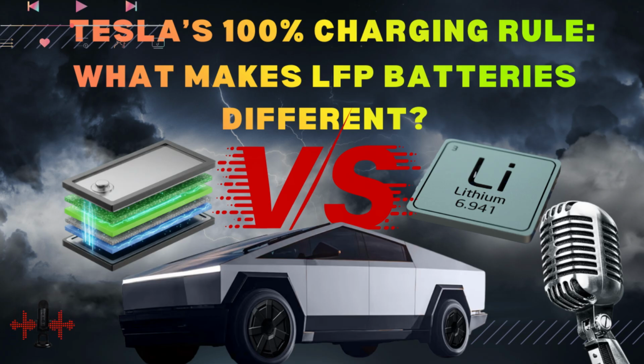But LFP behaves differently. This is where the famous flat voltage curve comes in, right? Yes, the LFP voltage curve is notorious for being flat across a huge range of its capacity, especially in that middle section, from roughly 20% to 80% charge. The analogy we came up with is this. Trying to measure the energy in an LFP cell is like trying to measure the water level in a very, very wide, shallow swimming pool. Okay, yeah, that would be tricky. It's incredibly tricky because a massive difference in the volume of water only translates into a tiny, almost imperceptible change in the water level, or in this case, the voltage. So if you're just glancing at the pool level, it's almost impossible to tell if it's 60% full or 70% or 80%. The change is just too subtle.